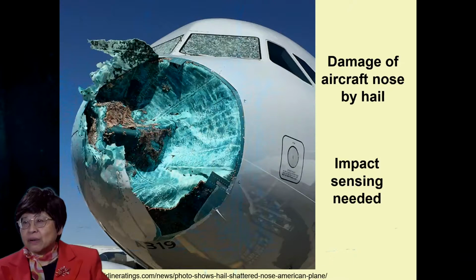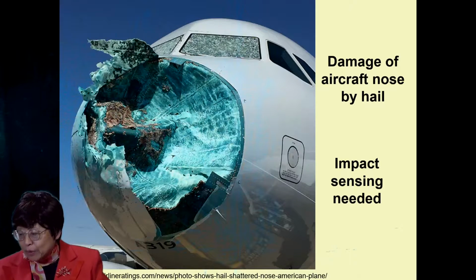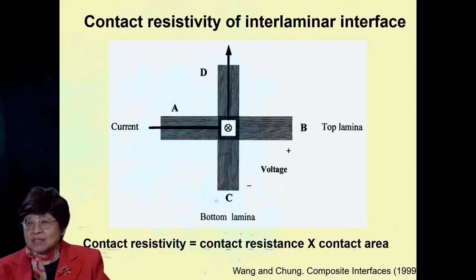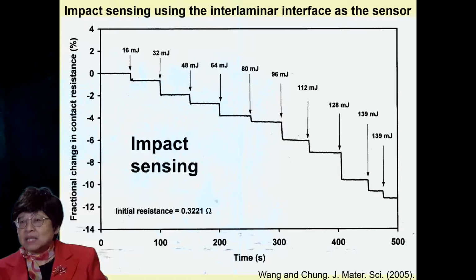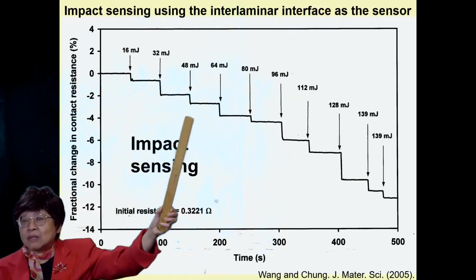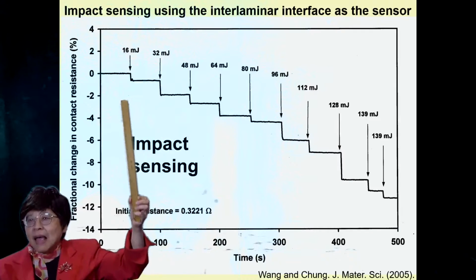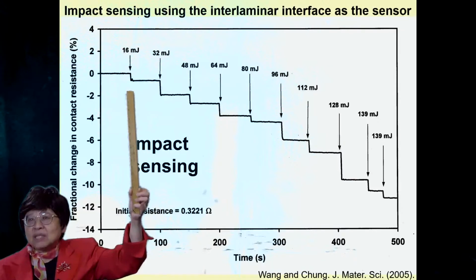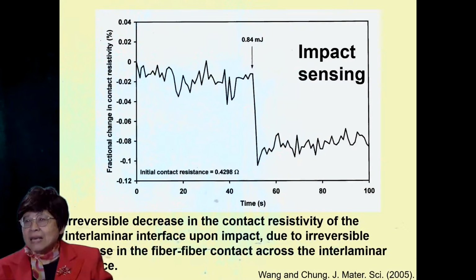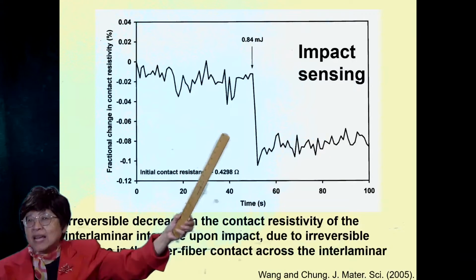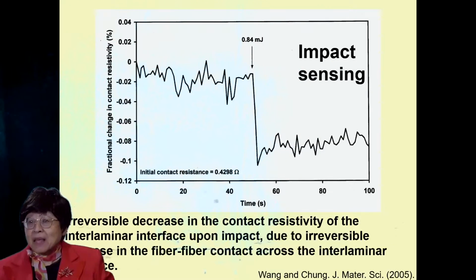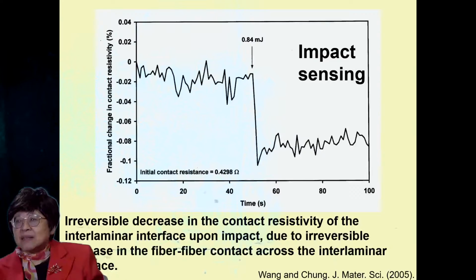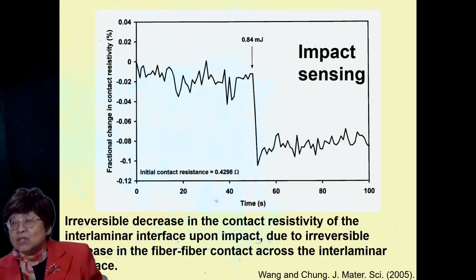Damage of aircraft can occur due to impact, such as that by bird or hail. And the contact resistivity is very sensitive to the impact. This shows the contact resistivity upon impact at increasing impact energy, and every time one impacts, the resistivity goes down irreversibly. Even at a tiny impact energy of 0.8 millijoule, we can detect it. The irreversible decrease in that contact resistivity is due to the irreversible increase in the fiber-fiber contact across the interlaminar interface.